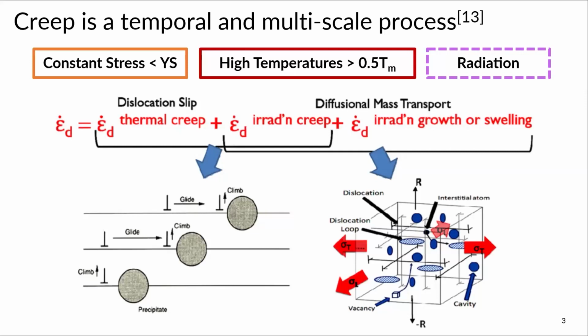And so there's 2 primary ways that creep is kind of being defined, and that's climb and glide. And so you have your initial crystal, which is your array of atoms. And so you introduce a strain by introducing extra rows or planes of atoms or taking them out. So glide is when that plane of atoms moves left or right in your material until it reaches an obstacle, which you can see is that gray circle, which you can consider a precipitate. And so once it reaches that obstacle, it wants to move to a lower stress state. So sometimes it will climb to another plane of atoms and then continue gliding, so continue moving.